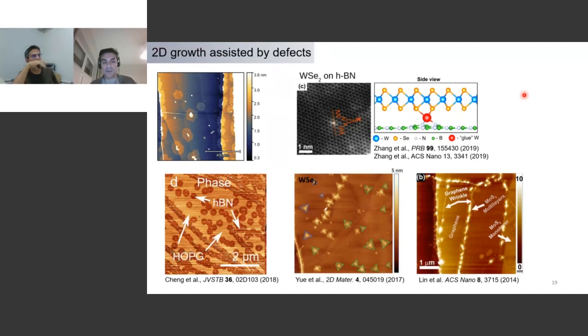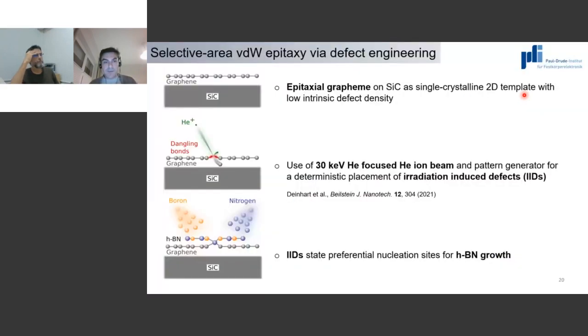And that's what we observe, for instance: when we grow for a long time, we do see that we grow HBN, a few layers, but we still have vertical growth going on. And these are things that we want to avoid. The question is, can we play a bit with defect engineering in graphene so that we can improve the situation in terms of nucleation? Can we create a method that would allow us to exert control of this process? And that's what we tried to do here.